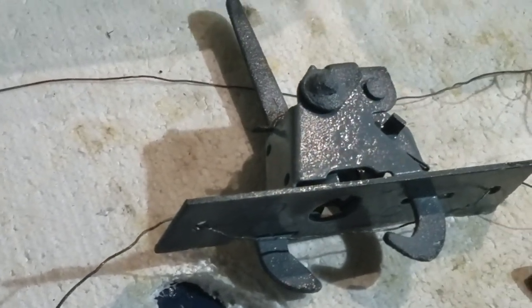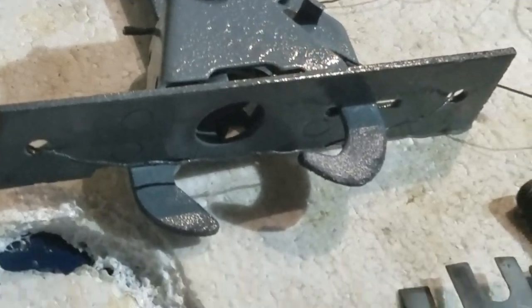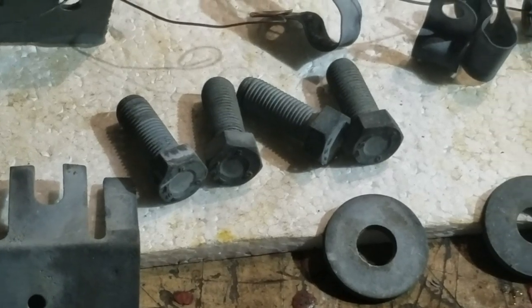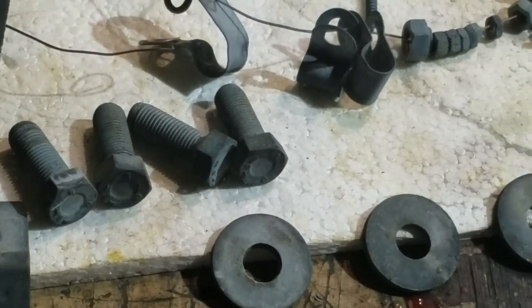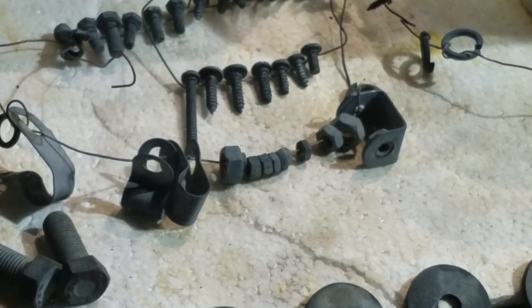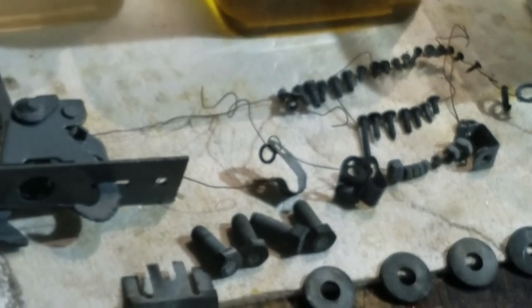You can see that these parts look far from being perfect. That's because they were heavily rust pitted when I pulled them off the vehicle. I've chosen not to go for the bright finish because they won't look good. Instead, I've gone for a more durable, heavier zinc coating which will give them, hopefully, another 25 or 30 years of protection.